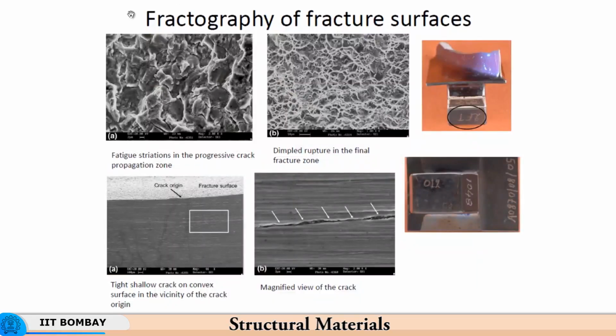And when you look at the fractography of the different fracture surfaces, what you find is that there is a ductile fracture. So this is a final ruptured fracture, and here you have fatigue striations in the progressive crack propagation zone. But then by and large this also shows some good evidence of ductility, because this also shows some dimpled fracture, and further probing into the